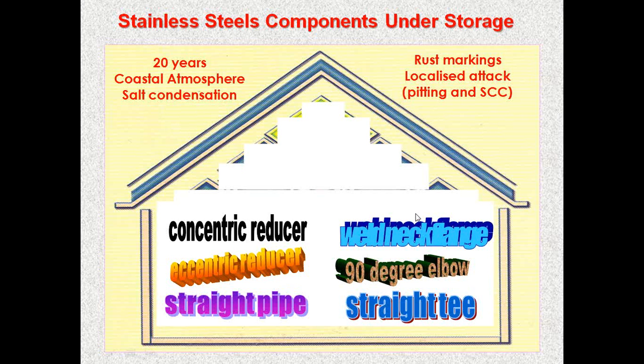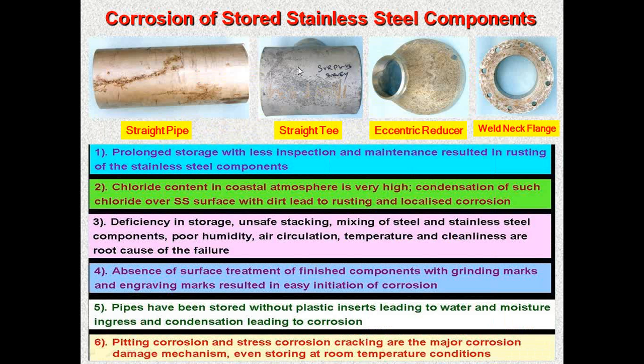So when we opened up the storage place to see the stainless steel components, what you will be surprised by, and it's amazing to see, is that the pipes have stress corrosion cracks, and you can see the straight tee, the eccentric reducer and the weld neck flange. They are all rusted. No one believes that it is stainless steel. It looks almost like alloy steel or steel. That is mainly because they were never preserved. Prolonged storage with little inspection and maintenance resulted in rusting of stainless steel.